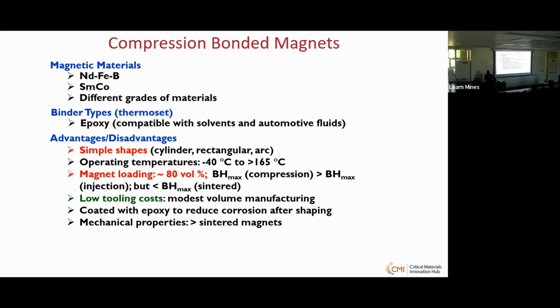So the compression molded bonded magnet, instead of mixing with the nylon or PPS and making a composite, I'll show some pictures, you are using it with the resin. So you take a magnet powder, mix it with the resin and press it in a press with a magnetic field. I'll show the picture in the next one. Epoxy is used. But you can make only cylinders and simple rectangular shapes, arcs. So you cannot make complex shapes using compression molding.